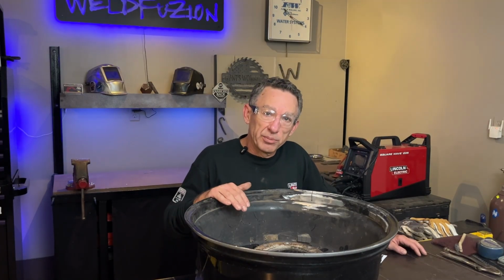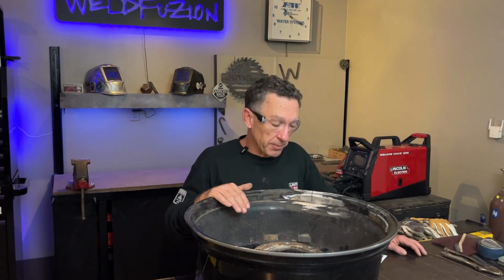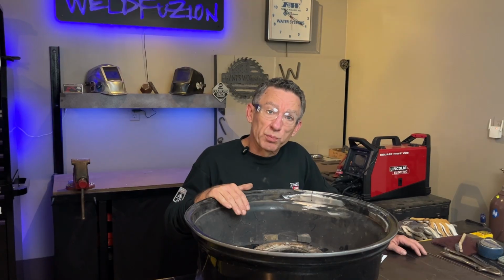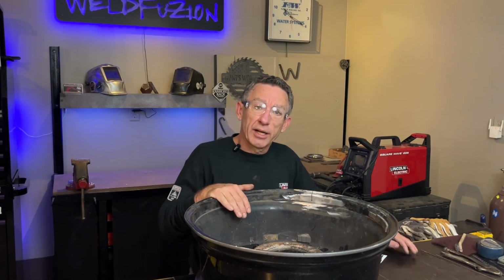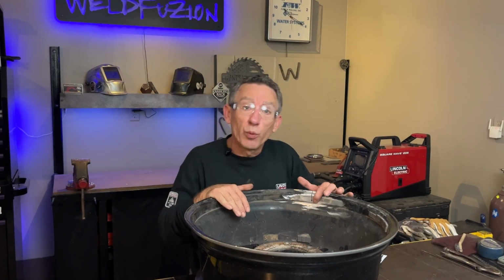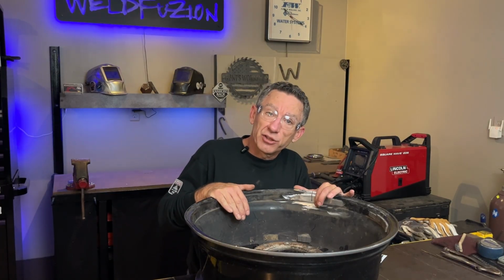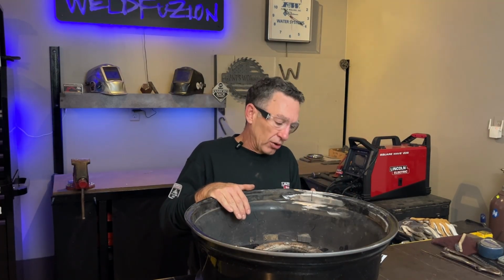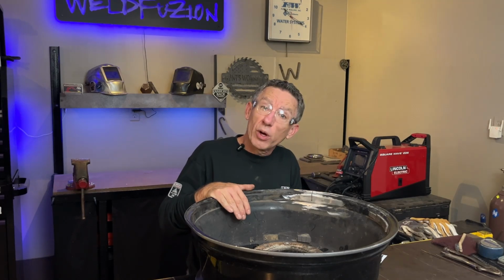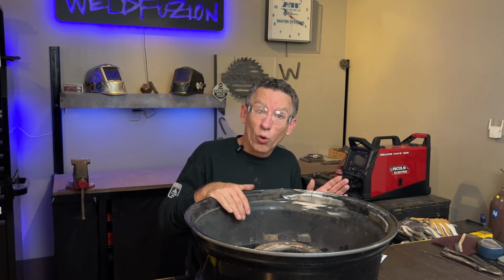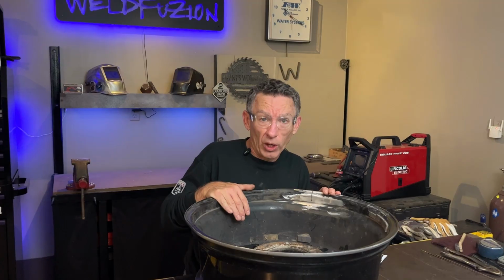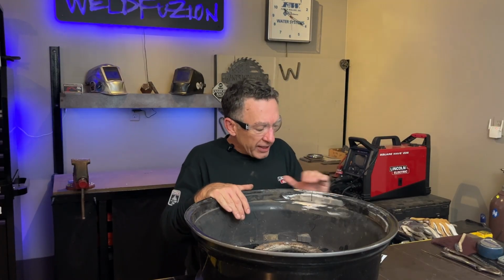Perfect. Okay. So let's recap. We've got this off-road rim here that's going to be used for non-highway speeds. It was already repaired once. It was brought to us with a crack right down the center line of the weld. So what we had to do is a little bit of inspection. We found the end of the crack. We drilled it out with a hole about 1/8 of an inch in diameter. And then I used the Sawzall to cut right down the crack to that hole. That way the crack is not there anymore. Or you may say, I just made it worse, right? So we've cleaned it off.